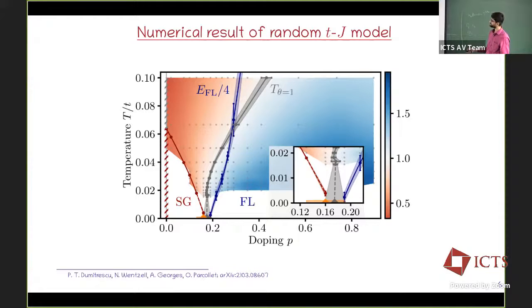So the y-axis is temperature, x-axis is doping. The color code is actually the exponent of the spin correlator, at least in this blue region. So this red region is slightly complicated. Here, if you focus in this blue region, what you see is that this gray line is the one that corresponds to the exponent being 1. So that's the SYK thing. And you see that it goes all the way down to 0.